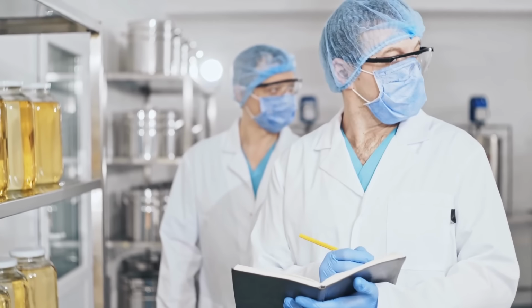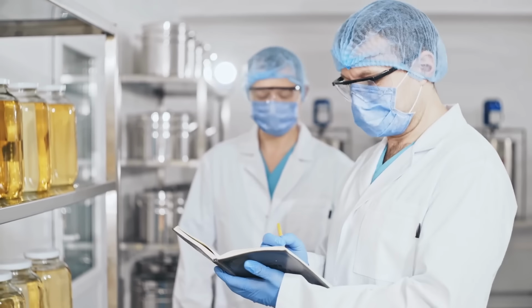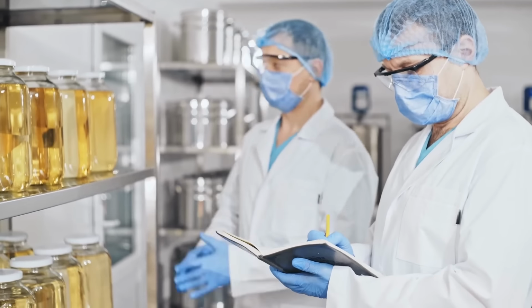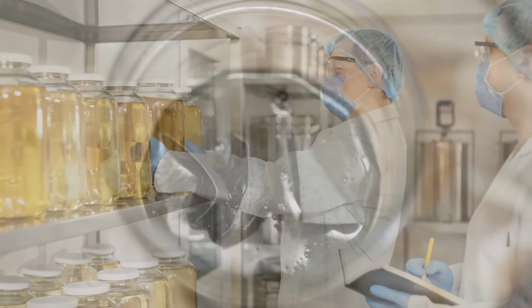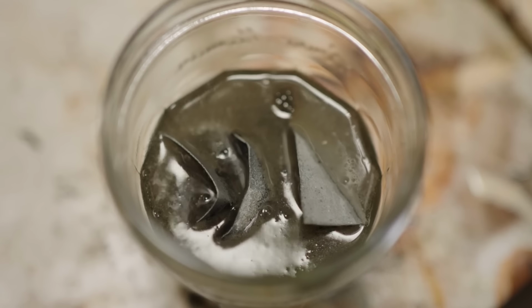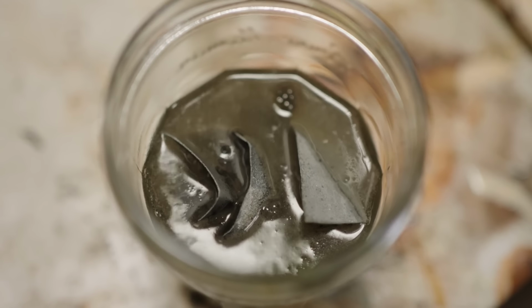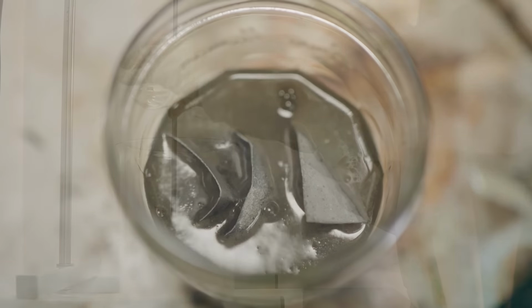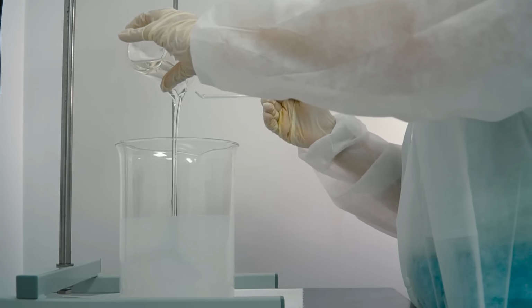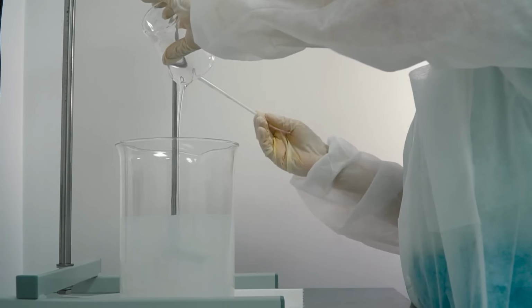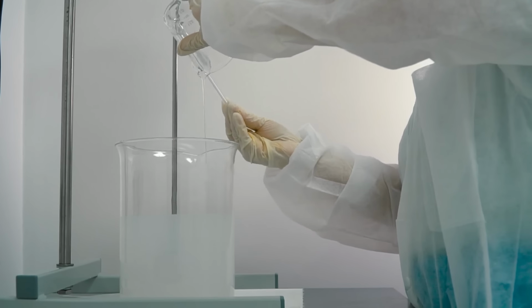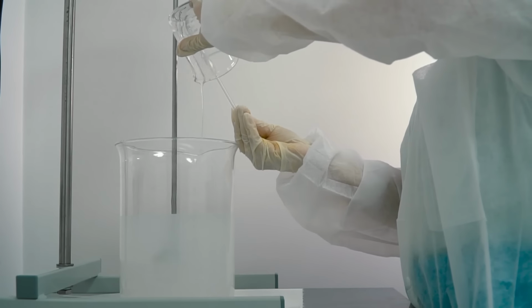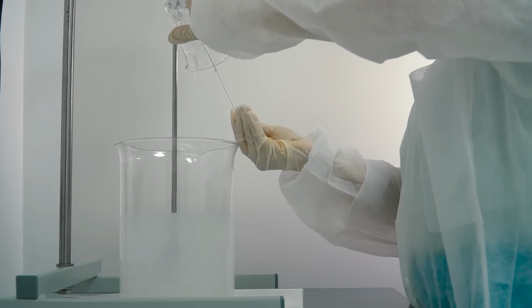However, titanium isn't chemically invincible to everything. There are certain substances that can penetrate or destroy that oxide layer. Hydrofluoric acid is one of those acids. This particular acid is the kryptonite of titanium and glass too, incidentally. Dilute hydrofluoric acid will attack titanium's oxide layer and dissolve it, allowing it to then react with the underlying metal. So titanium equipment cannot be used with hydrofluoric acid.